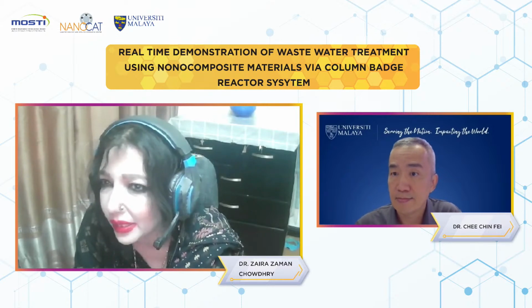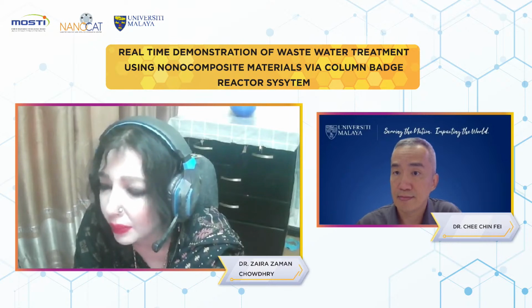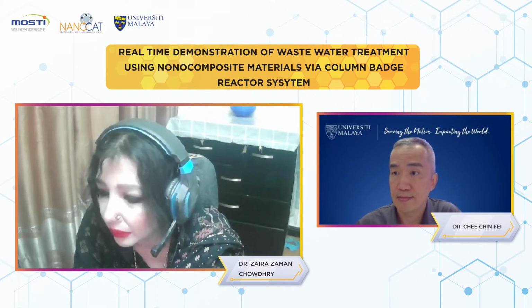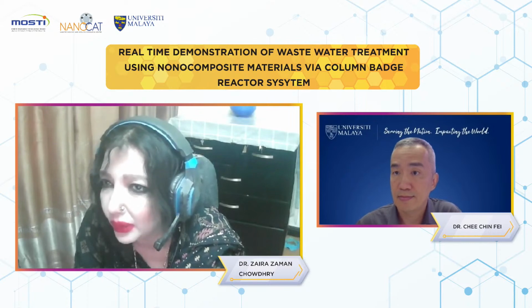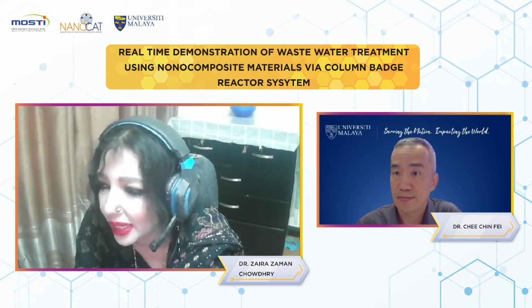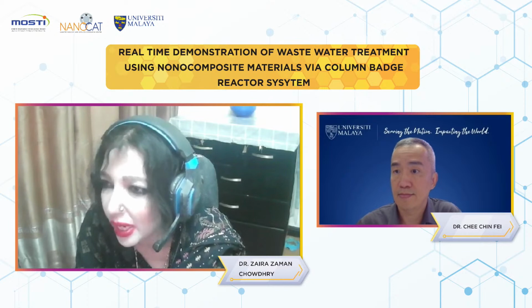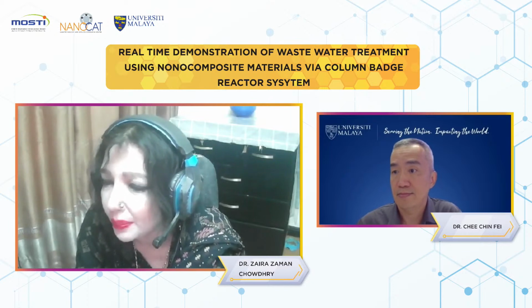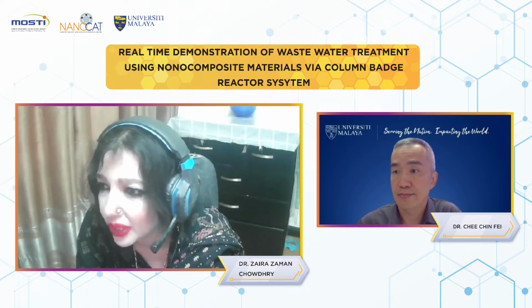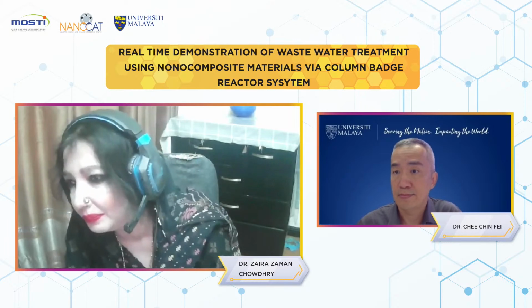We can use it, but in some processes, like ball milling. When we are making activated carbon to nanocarbon, at that moment we use anhydrous calcium chloride just to absorb the moisture, okay? Not for pollutant purification on a larger scale; we don't prefer calcium chloride for that.